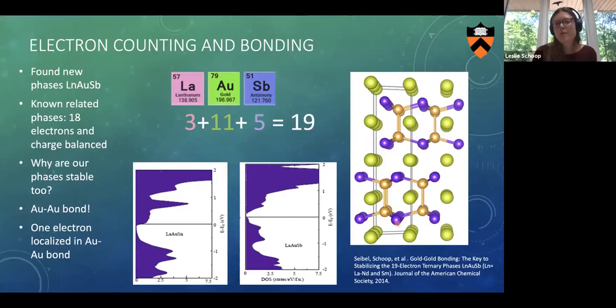And then if you input this crystal structure into a DFT code, you will see it also has a pseudo gap and is semi-metallic in spite of the 19 electrons. And so this 19 electron count is a formal electron count, because in reality, you would have to count two formula units per count. And then you can boil it down back to the typical 18 electron count.